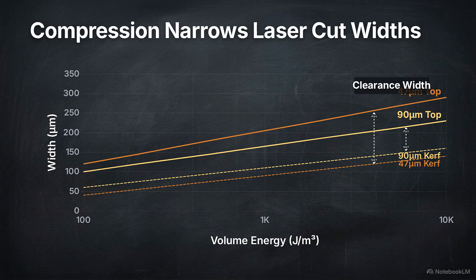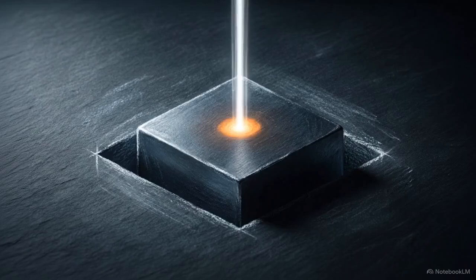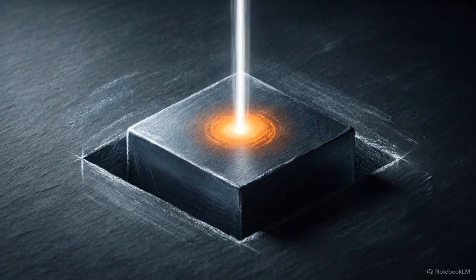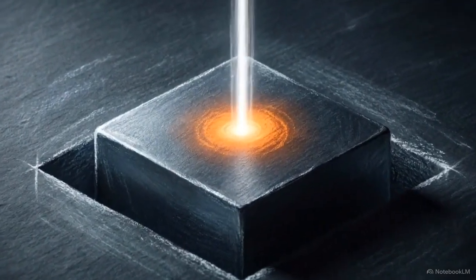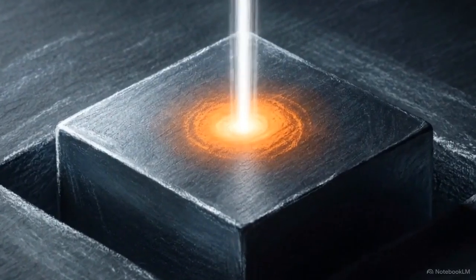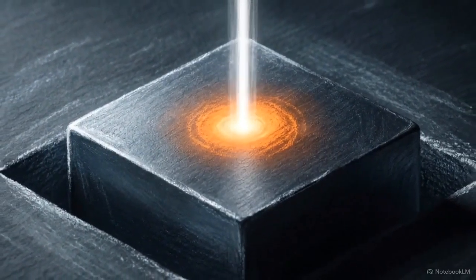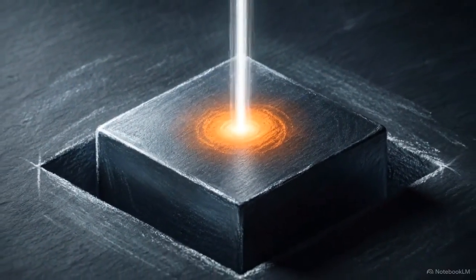Introducing the calendering process, this chart overlays 90 and 47 micrometer compressed electrode data onto our baseline. Across all volume energies, compressed electrodes produce significantly narrower top widths. That density demands power, requiring a much higher volume energy threshold just to establish a kerf width. Compressing the material mechanically alters how it reacts to thermal energy. The denser structure physically limits the heat-affected zone, protecting the surrounding active material.